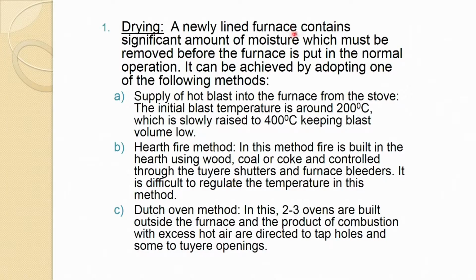A newly lined furnace contains a significant amount of moisture, which must be removed before the furnace is put in normal operation. This is a very critical and important step, and one has to make sure all moisture is driven away. The time spent in this is worth it rather than regretting later when some problem comes up during the operation of the blast furnace. So, it is worth spending time on removing the moisture completely from the bricks and other places. This can be achieved by adopting one of the following methods.